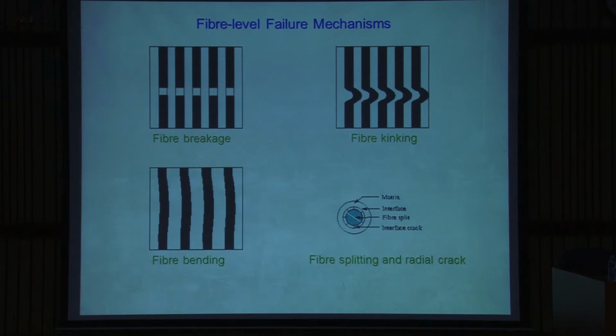These are the pictures which symbolically show the fiber breakage. These black lines are the fibers, and the remaining part is the matrix. There can be a fiber breakage at one place, and then it can happen in subsequent places. This is one of the ideal cases I am showing here. In practice it may not happen like this, but one fiber fails, and in the neighborhood of that there is a stress distribution and the neighbor fibers fail. This is fiber breakage. This happens when the longitudinal strength of the fiber is exceeded. At that time it fails. This is one of the reasons.